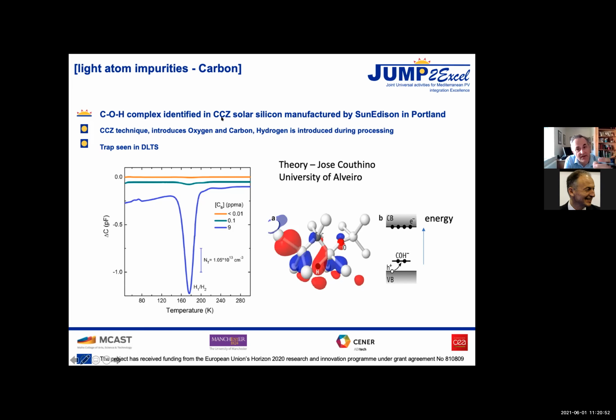But it does mean that certain impurities tend to build up. The whole idea of Czochralski is the impurities stay in the molten silicon. That's why it works. That's why you get such pure silicon. But certain elements don't do that very well, and one of those is carbon. And so we have a high level of carbon in their material, still parts per million, but higher than normal.